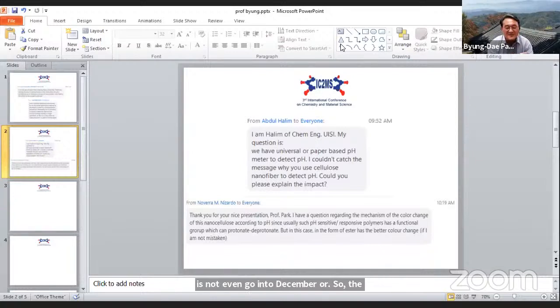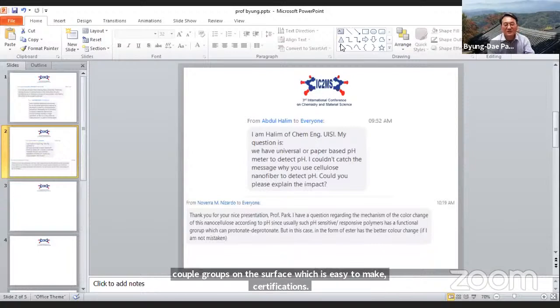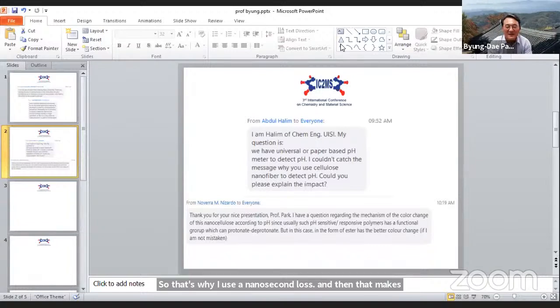So the idea is I use the nanocellulose as a carrier because nanocellulose, CNC or CNF, have carboxyl groups on the surface, which is easy to make esterifications. So that's why I use the nanocellulose, and then make it react to the pH indicator as a carrier, and then make this film, which can be used as a kind of indicator in the future, for food storage or those kind of things.